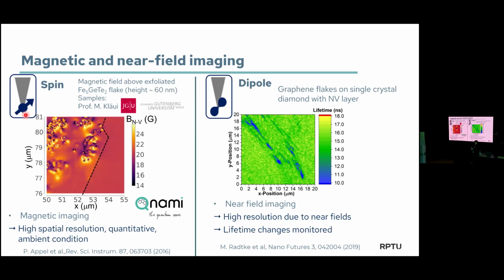Just sometimes you look at the stray field images and you think, this is not what I expected. But then you have to keep in mind that we are not measuring the component that comes out of the plane of your sample, but we're measuring the projection under an angle. And if the field comes out under a certain angle and you're scanning over it, you always have to keep in mind that you're projecting under that angle. It sometimes makes things look asymmetric that you would expect to be symmetric. Exactly.